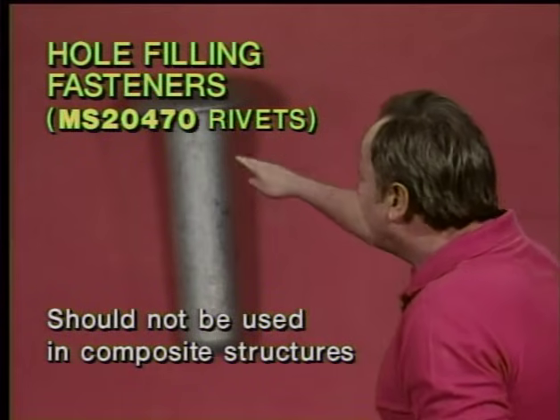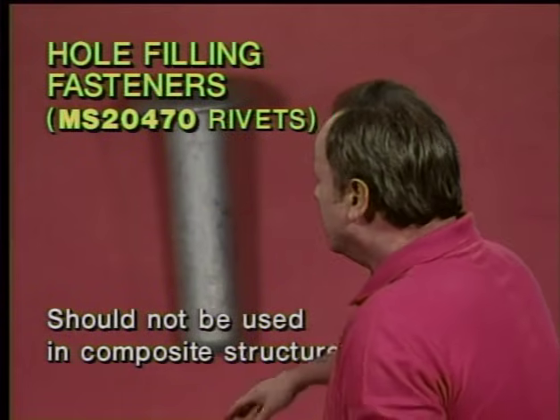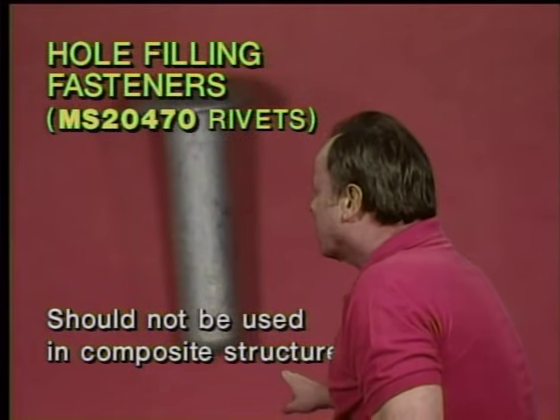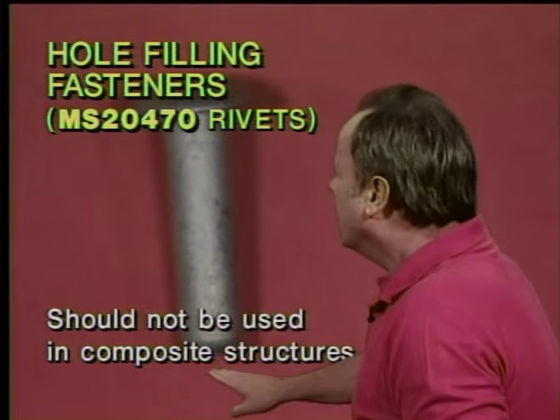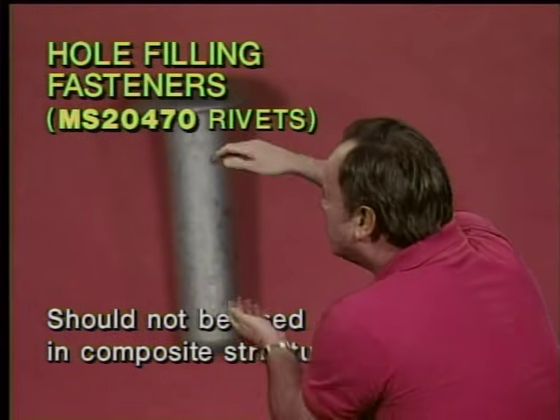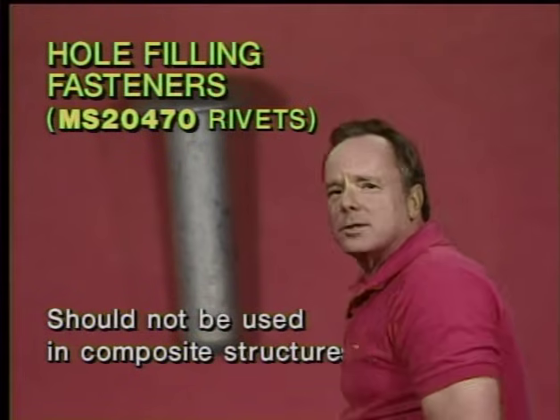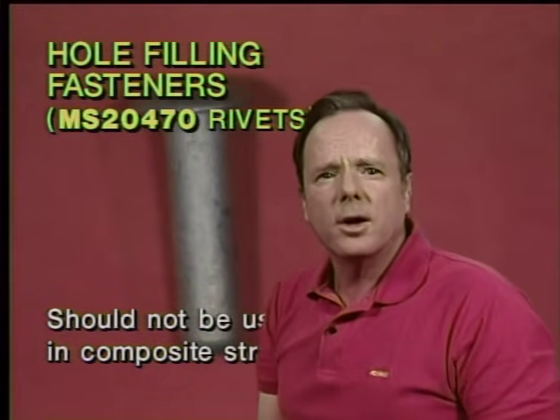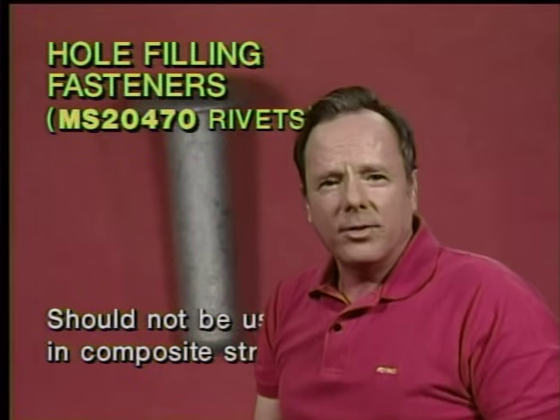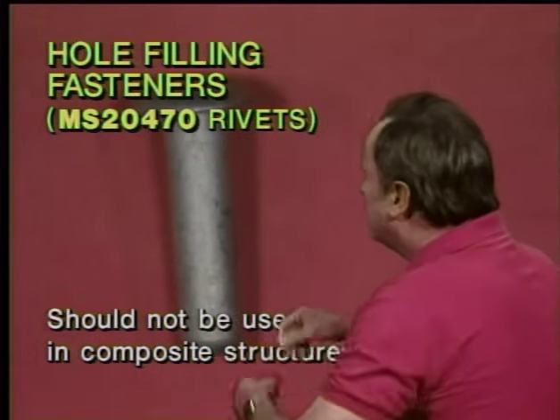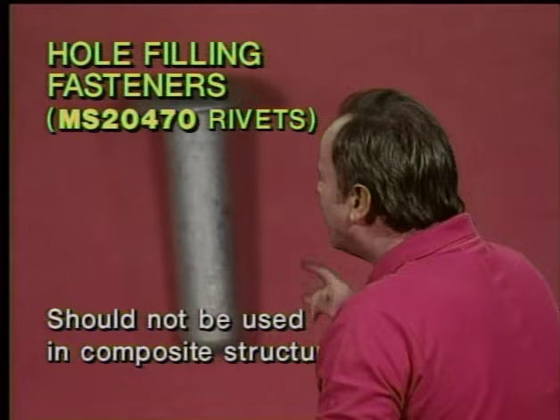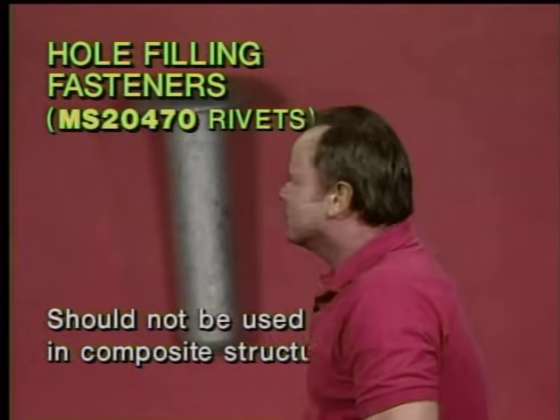Now take a look at this. At first blush, I'll bet you think that that is a rivet. Well, it is, but on the FAA written exam, they will also call it a hole-filling fastener. And the FAA wants you to know that hole-filling fasteners like this rivet should not be used in composite structures. Now we're talking about fiberglass or Kevlar. And the reason is when they are bucked, they can expand against the sides of the laminate of the composite structure and cause delamination at the edges of the hole. So they expand and damage the composite.